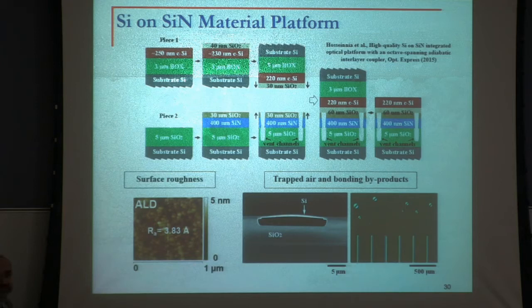Now, if silicon nitride is so good, why don't we use silicon nitride only? The problem is that we cannot reconfigure or tune silicon nitride easily. It's a dielectric, so I cannot inject carriers. Carriers are out of the question. Its thermo-optic effect is weak, so I have to apply a lot of heat to change it. So now we have a material like silicon that can be modified more easily. We have a very low loss material, silicon nitride. So now the marriage of the two should give us a much better material platform. And that's what we did.